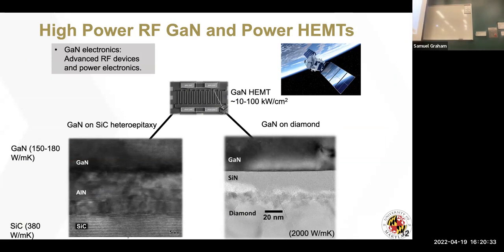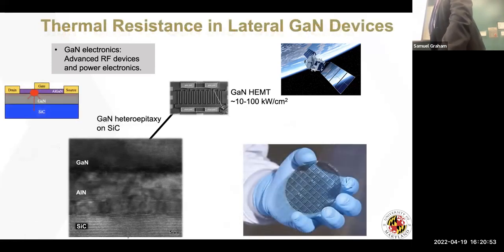This material right here has a thermal conductivity of about 380 watts per meter K. I can go to diamond, which is about 2,000. But again, I have to put another material in between them in order to get them to grow together or to bond them. And so I have to worry about that particular layer in order to reduce the thermal impedance. So one of the things that we've been doing is saying, is there any way that we can get rid of the aluminum nitride altogether?